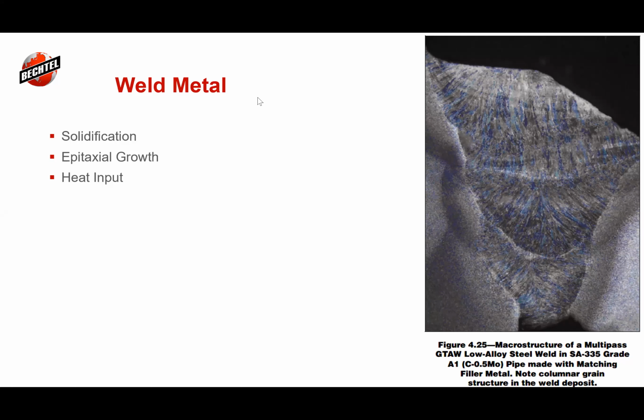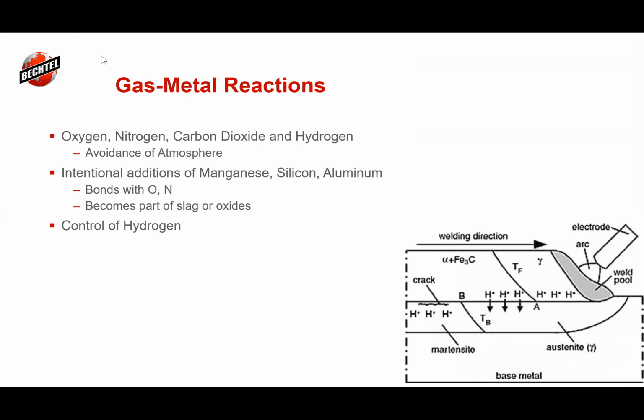So we have a direct effect and a correlation between that weld metal and the heat input and the HAZ. All of these get stitched together to how it's going to work. And I had to put this in here on gas metal reactions, because I think that we can't just talk about the heat affected zone. If, for example, our weld metal is much stronger than our heat affected zone, then it makes the heat affected zone the weak link.